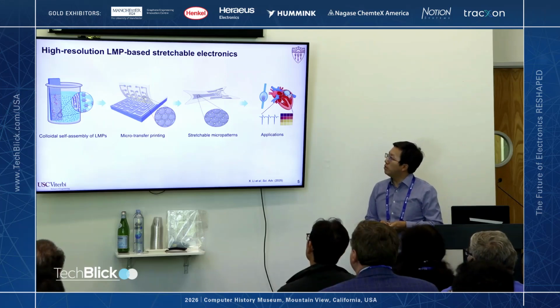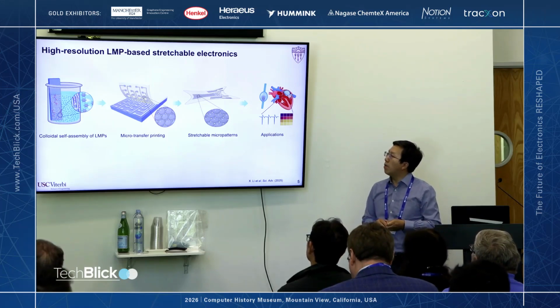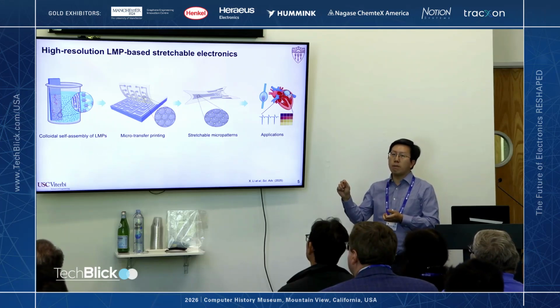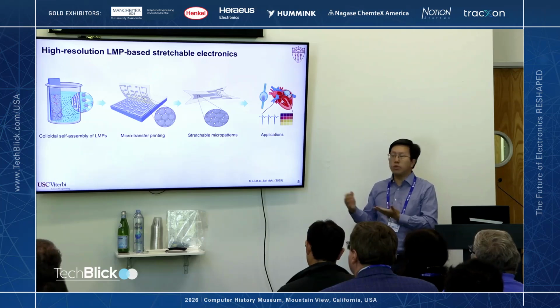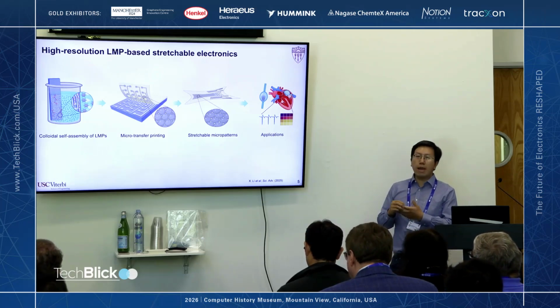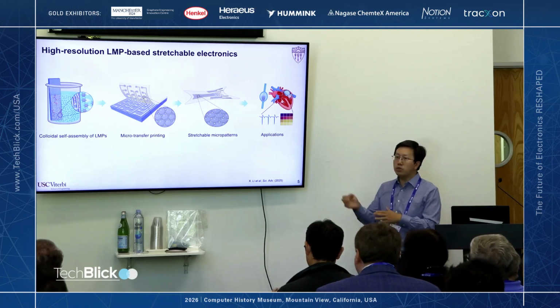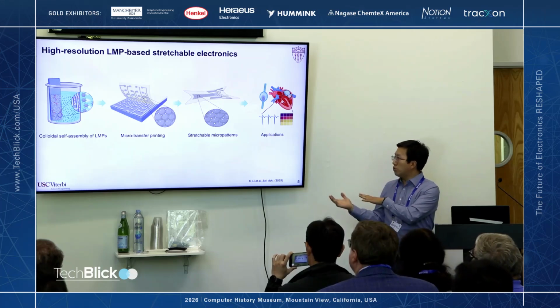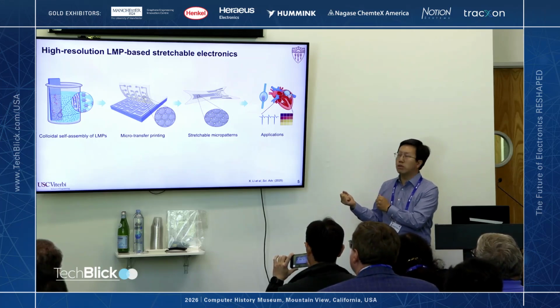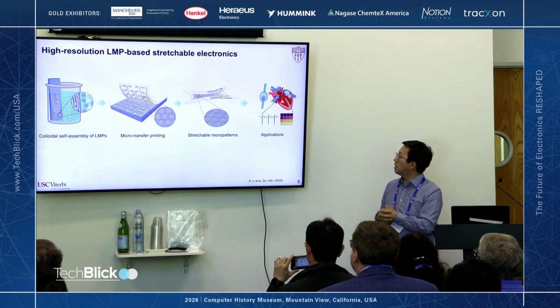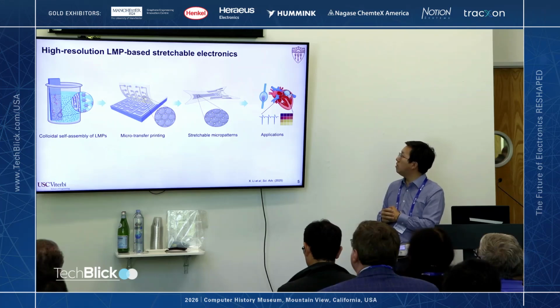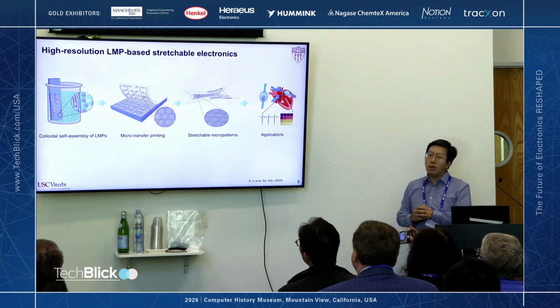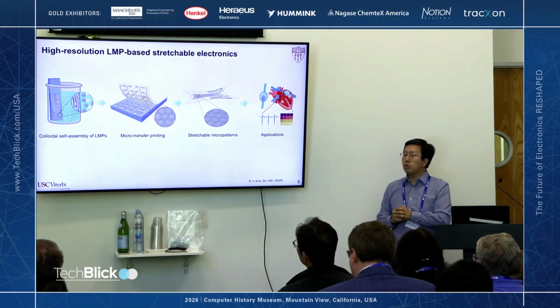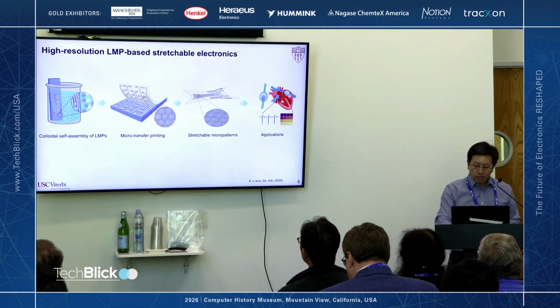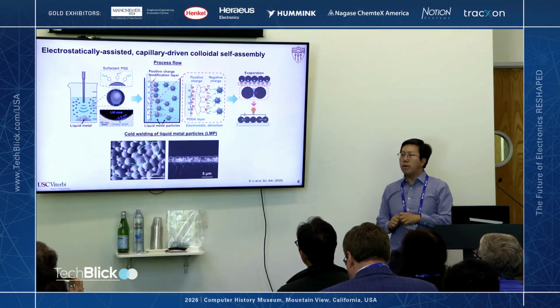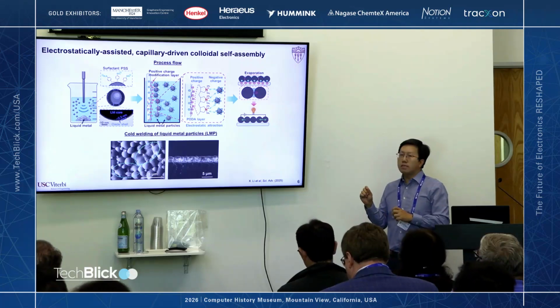First, we developed a unique colloidal self-assembly process where we can form a single layer of liquid metal particles and also sinter them during the assembly process. We can do this on our patterned substrate so that we can transfer the patterned liquid metal particles onto a soft elastomer as our substrate. We did many different characterizations, mechanical and electromechanical, and we also demonstrated that we can integrate this liquid metal electronics onto surgical tools for cardiac mapping.